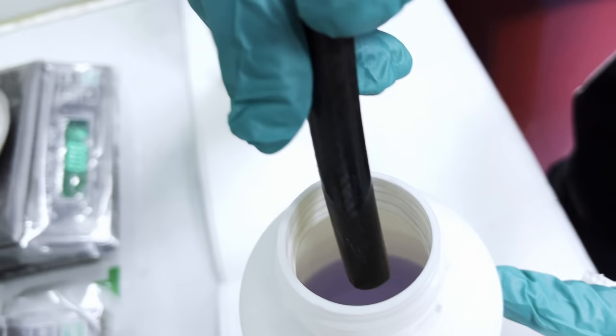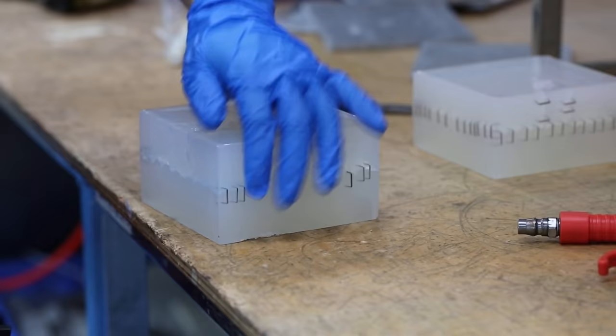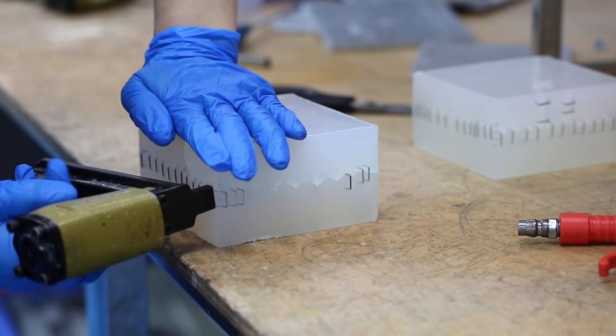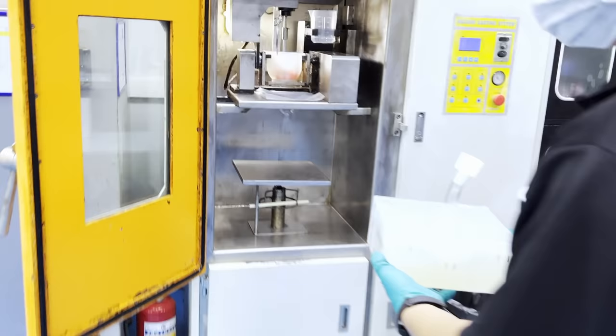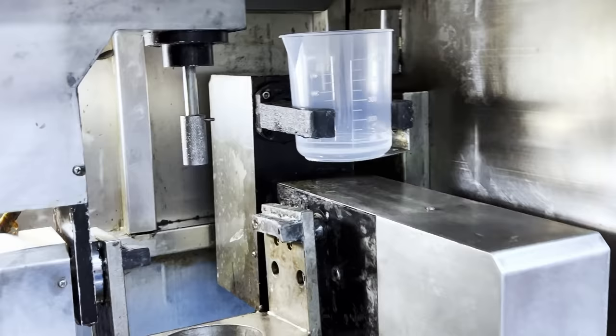Also, after pouring out our resins into the casting cups, we make sure that the bottle is backfilled with argon gas before putting it back into the storage oven. This keeps it from absorbing moisture, which is a blowing agent for polyurethane. Not a good idea unless you want to make foam, and believe me, this is probably one of the biggest hacks in this process. Now we preheat our new silicone mould halves to around 70 degrees centigrade, then we spray on some silicone release agent, put the two halves of the mould back together, and staple them shut. Then the tool goes into the vacuum casting machine, we insert the pouring funnels, connectors, and tubes, and put the A and B parts of the resin into the pouring cups.